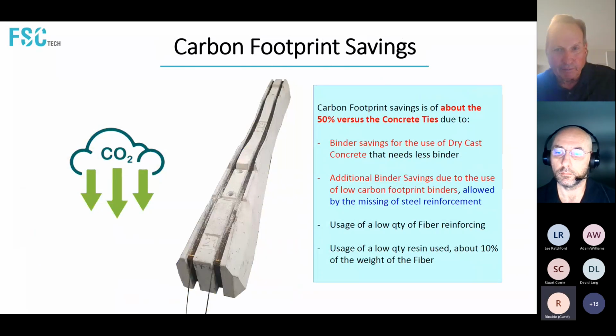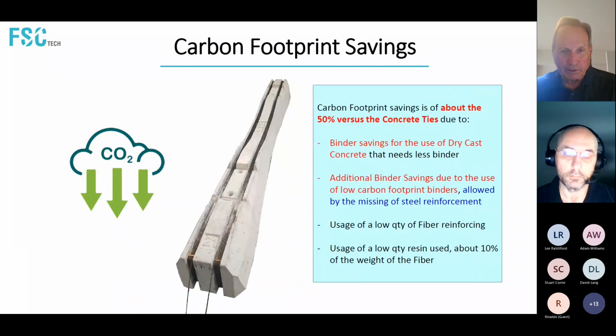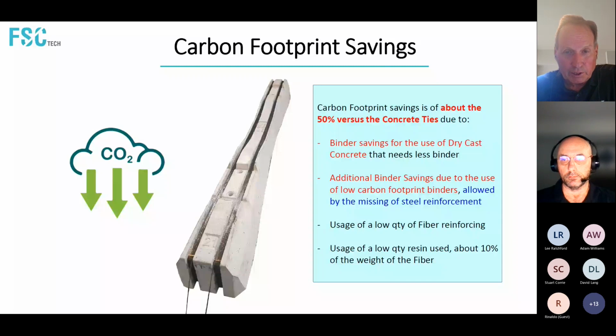Carbon footprint savings. So there's binder savings by just not using so much of it. You use 25% less. You can also add to that by utilizing low carbon footprint binders. And really, compared to steel, we're using a low quantity of fiber reinforcing, and some of that's due to putting it right at the surface. And then there's also a small amount of resin used, about 10% of the weight of the fiber. But together, the fiber and the resin have a much lower CO2 footprint than the steel reinforcement does.